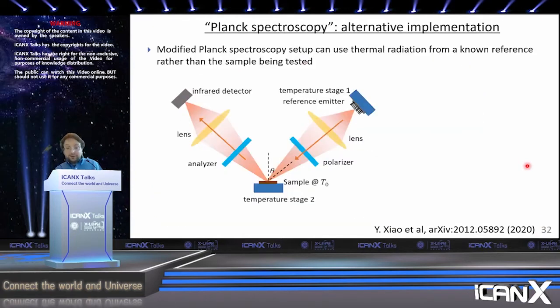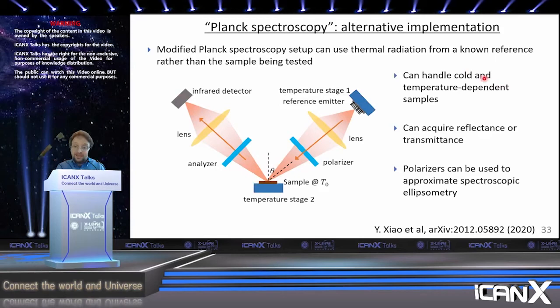I should mention that there is an alternative implementation of Planck spectroscopy that's possible, although we haven't demonstrated it experimentally yet, where instead of looking at thermal emission from the sample itself, you can look at thermal emission from a reference. So you can have a temperature stage over here that changes the temperature of the reference. You can send that light to the sample and look at the reflection or the transmission through the sample. And that enables you to handle samples that are cold, that don't emit very much, or that have temperature-dependent emissivity. You can also use this, of course, to acquire reflectance or transmittance spectra, which might be useful.